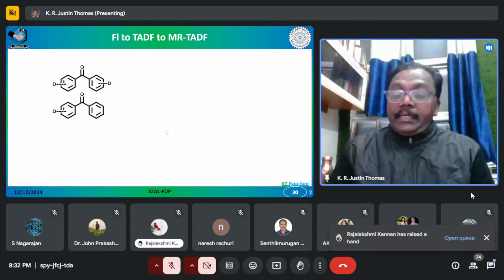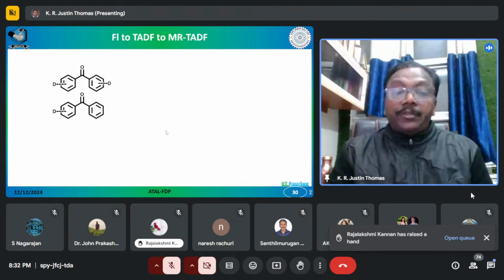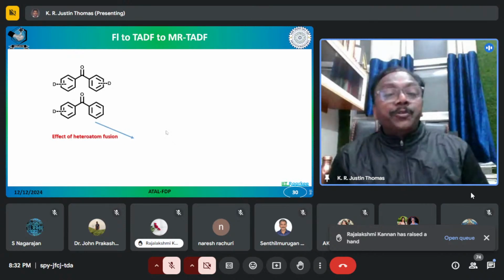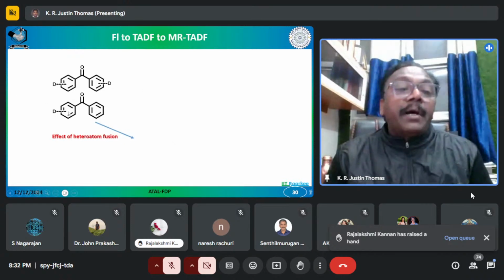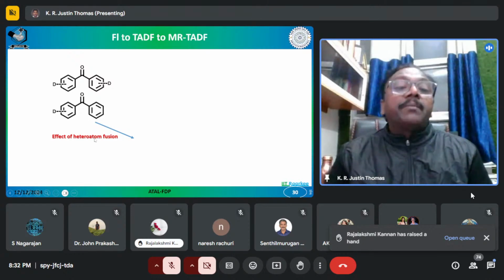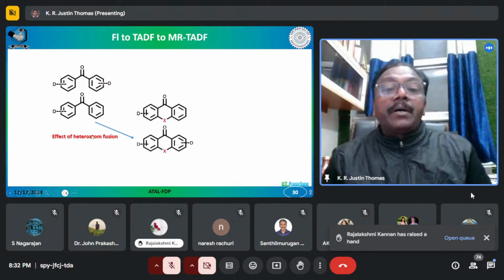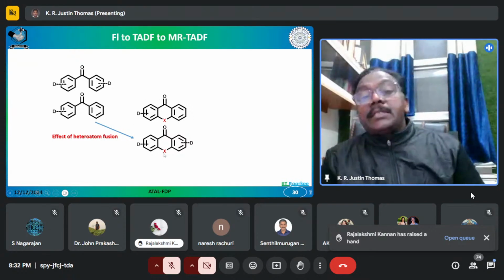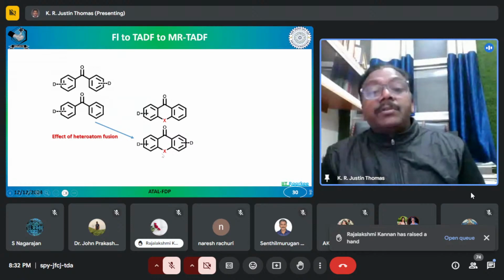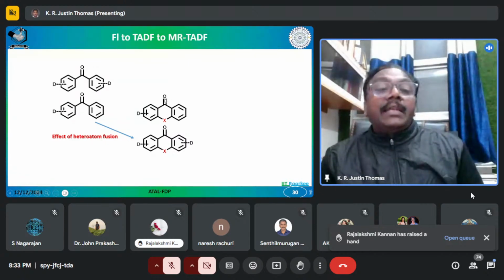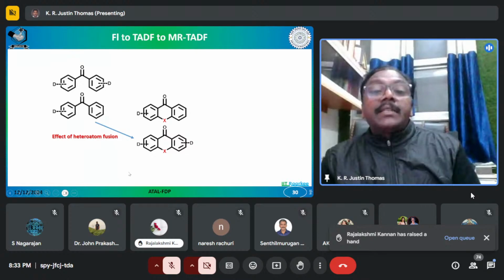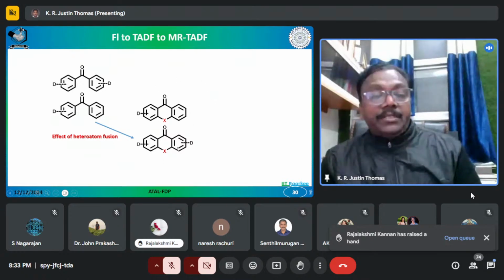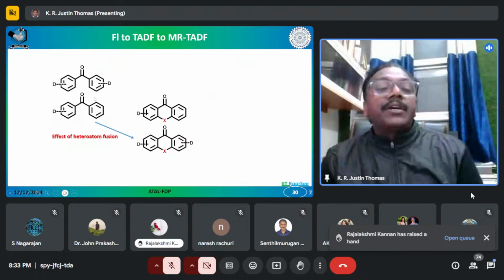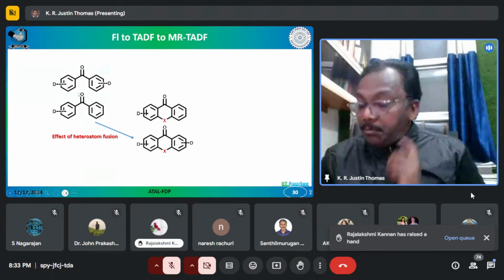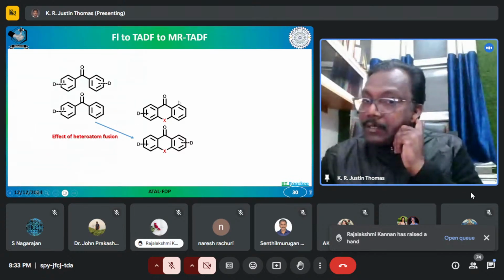And you can have donors on this benzophenone. However, when you are doing a fusion of the benzophenone at this point with a heteroatom or with a carbon, you can have different molecules. The molecules will have a structure something like that. If the X is carbon, then you will have an acridone kind of molecule. And the moment you have a fusion here, you see that these molecules are now TADF in nature. A very good transition of a fluorescent or phosphorescent molecule getting converted to a TADF molecule.